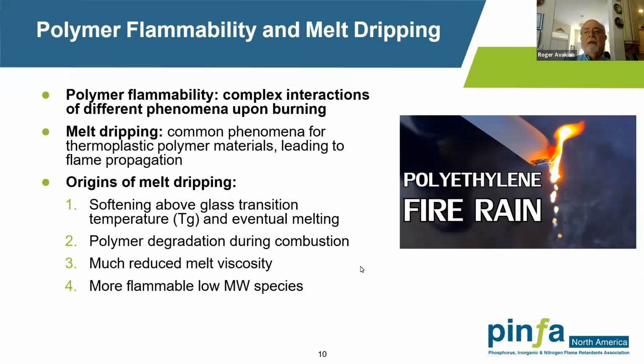Typically, you can see this on the diagram on the right: polyethylene burning, and you see the flaming drips. And this is the other issue. It becomes even more of an issue when we talk about the Underwriters Laboratories 94 test, particularly in the vertical orientation. So what drip suppressants do is basically impede, retard or prevent this dripping behavior. And the dripping can be either a burning drip or a non-burning drip.